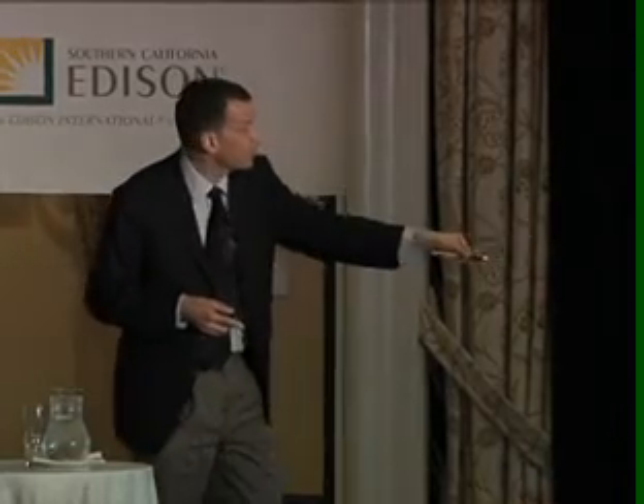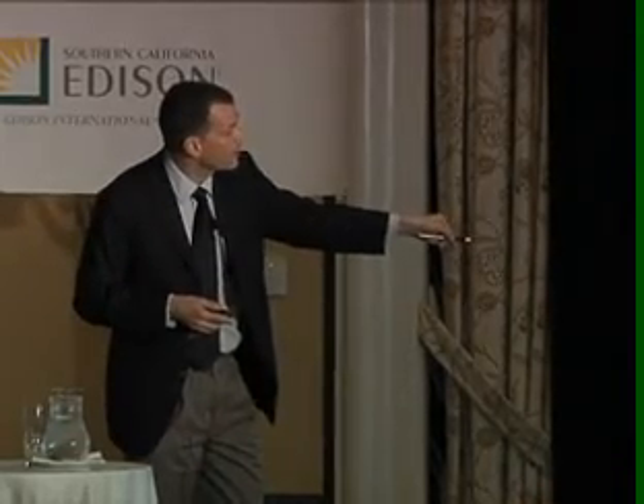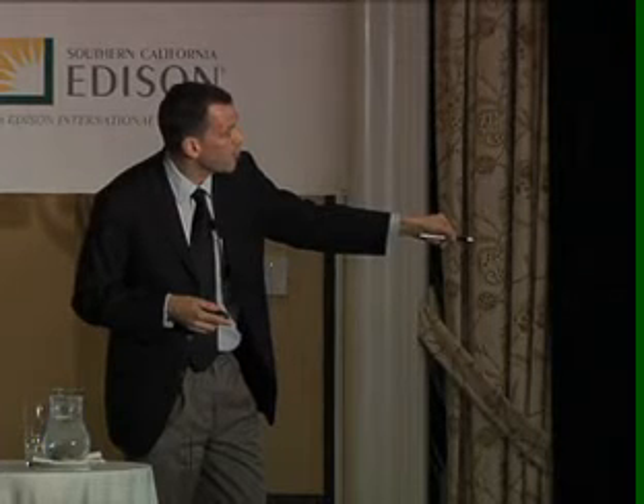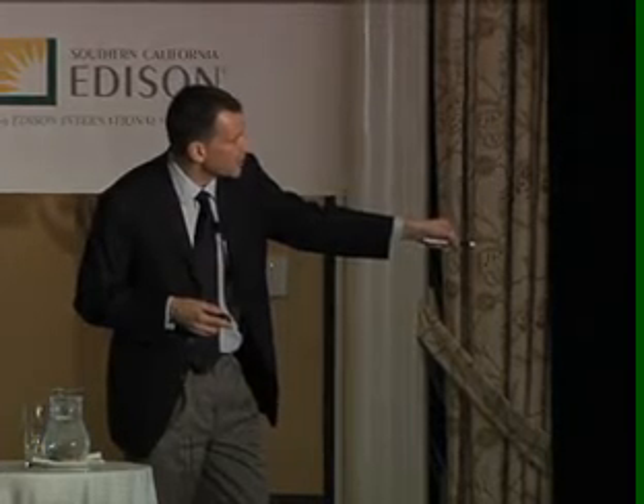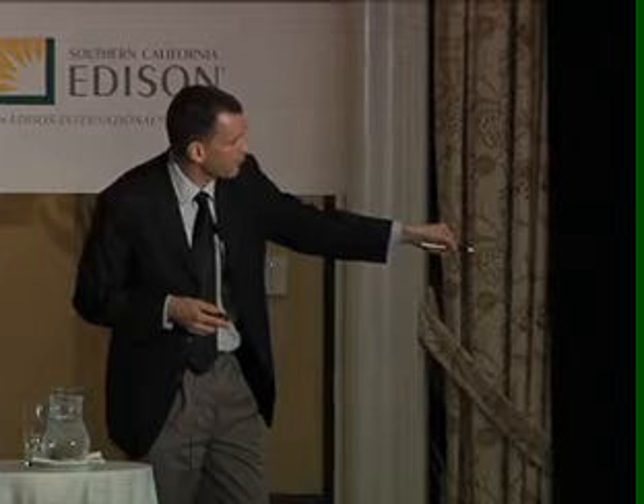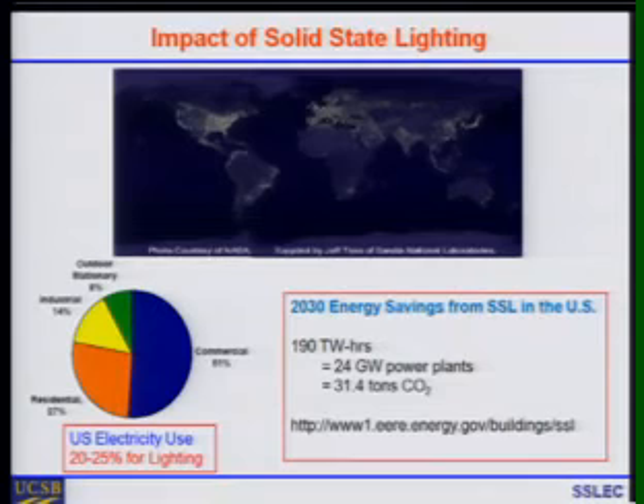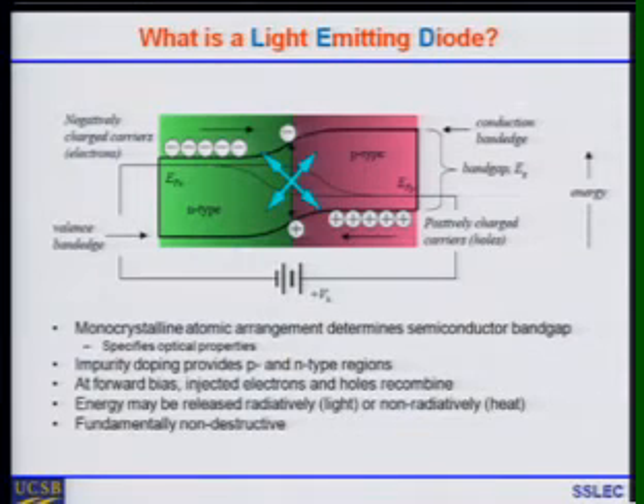At 150 lumens per watt, what you will find is that DOE estimates 190 terawatt hours of energy savings. So that's the equivalent of 24 full gigawatt power plants. Almost all power plants are on the order of a gigawatt, or about 31 tons of CO2. These conservative estimates are based on 20 to 25% energy consumption. So just to change gears a little bit, how do we make light from LEDs?